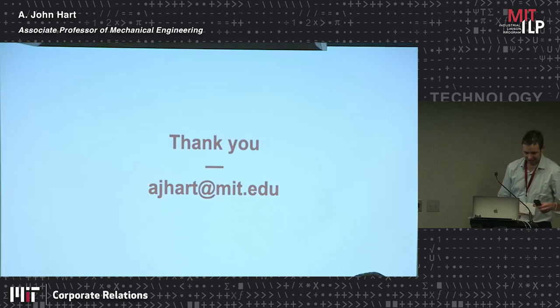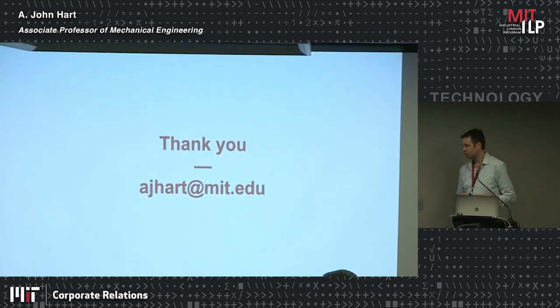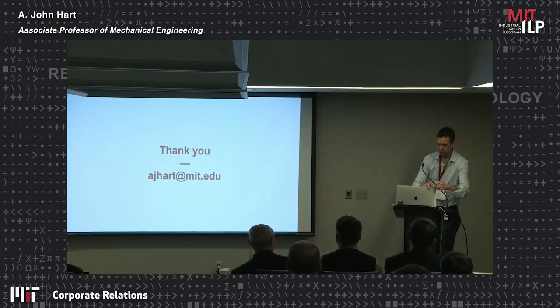Question: What is the subset of metals that can be 3D printed now? Answer: A very wide variety — more than I could mention. Titanium, titanium alloys, and many but not all aluminum alloys. Another way to say it: in melt-based metal 3D printing processes you can print pretty much any alloy that is weldable or castable. In solid-state metal 3D printing techniques — those based on binding and sintering, more like conventional powder metallurgy — you can print another set of alloys not so conducive to melt processing, like refractories. Zinc and zinc casting alloys can also be printed with melt-based processes.